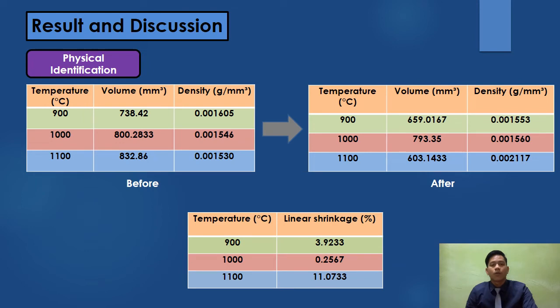So now, what we have for the results and discussion of physical identification: the volume of the sintered samples decreased about 10.75%, 0.87%, and 27.58% after sintering at the temperatures of 900, 1000, and 1100 degrees Celsius. This is because the eggshells are calcined at a high temperature for hours, which causes a reduced number of micropores of eggshell. The density was decreased after sintering at 900 degrees Celsius.